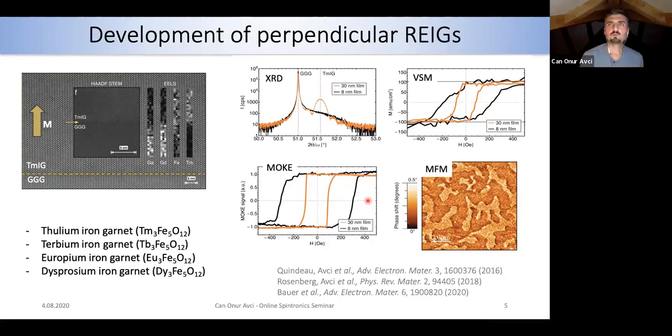So the domain walls, we can only calculate because we cannot right now measure it. I don't have the data, but what we calculated should be in the order of between 10 and 20 nanometers. But that needs to be confirmed by measurements. It also depends very much on the thickness. This estimation was based on a thin film that is like 5 nanometers.